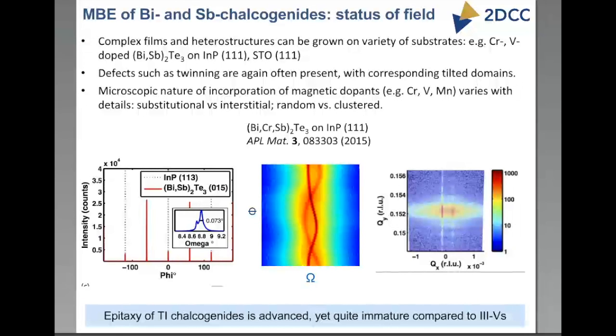If you do very careful X-ray diffraction scans, so if you do phi omega scans or triple axis scans, you can learn a lot about how these twins are distributed in the sample. You'll find, if you look at the middle image, which shows this very interesting color plot, each of those curved red lines is essentially showing you how the omega scans vary as a function of the angle phi in the X-ray diffraction scan. And it shows you that there are different domains that are tilted in different directions. So these are all kinds of defects that we need to figure out how to get rid of.